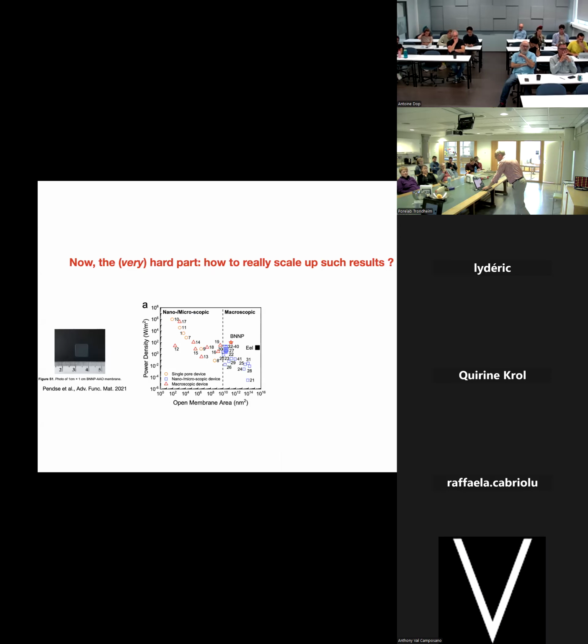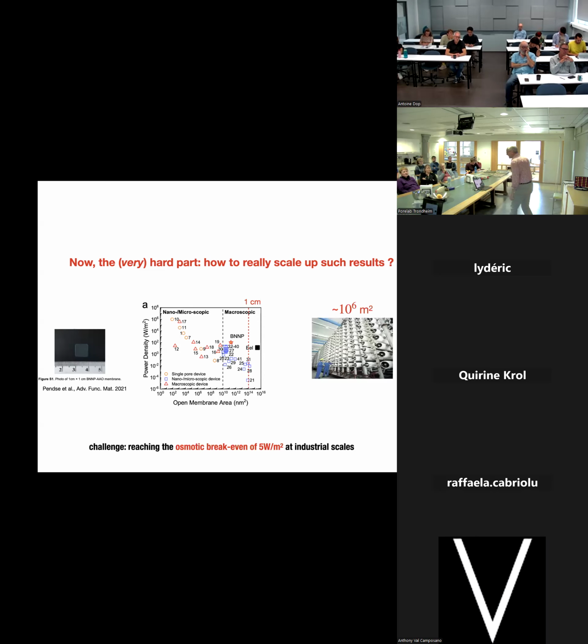And the problem is to scale up, really to scale up. Here, for example, is the paper by Pendse I was discussing. They looked at the power density versus the membrane area. Okay, so we are around here. And you see it's decreasing, and there are very good reasons for that. But if you put numbers, here this is a 1 centimeter membrane, and you want to have 1 million square meters. So there is still a huge gap. In practice, you want to have this kind of break-even of 5 watts, so 5 watts, actually, it's here. And you see most of these materials are completely unable to bypass that.